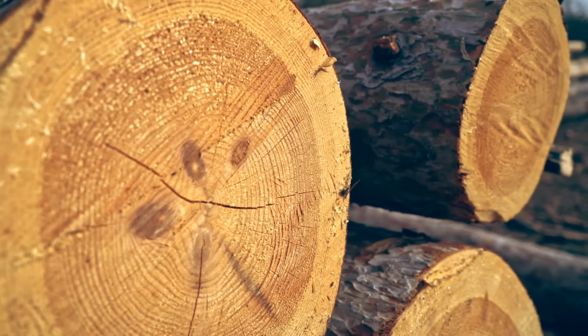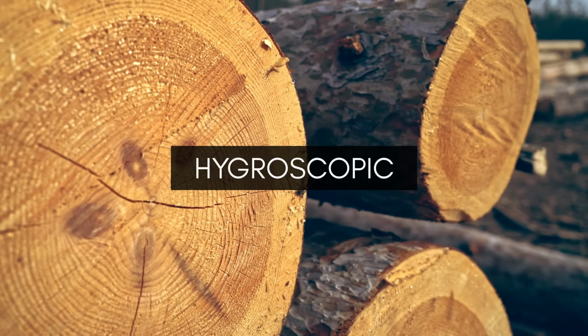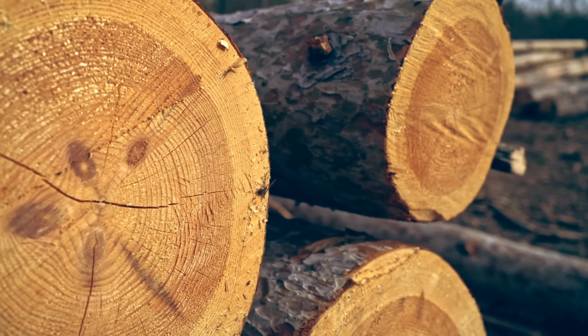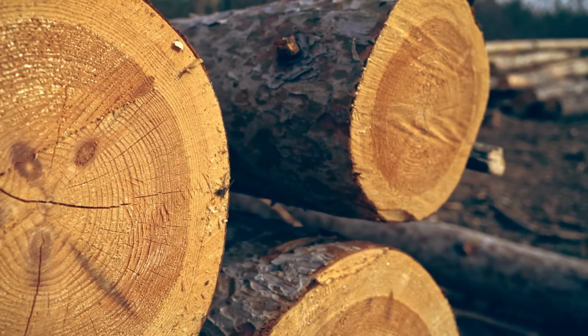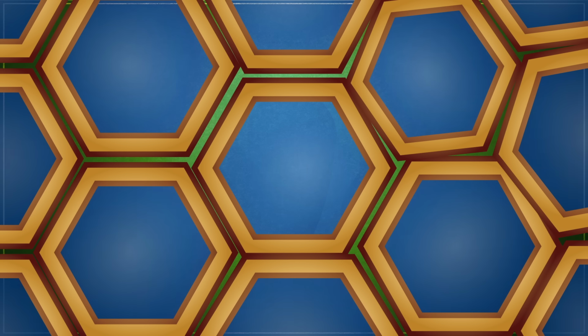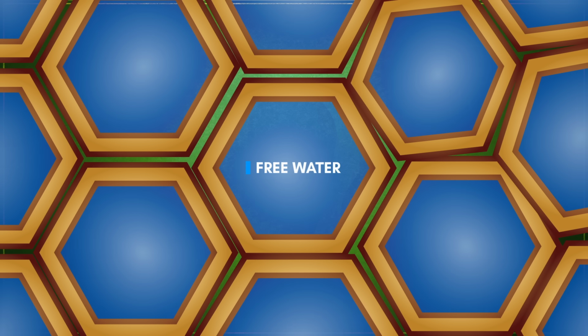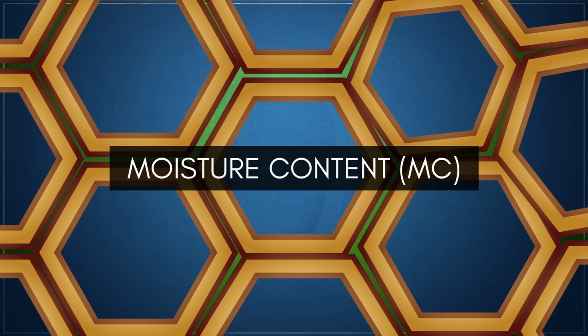Wood is inherently a hygroscopic material as it exchanges moisture with its environment in response to the ambient temperature and relative humidity of the air. Water exists within the cellular matrix of wood in two distinct forms: free water, which occupies the hollow cell cavities, and bound water, which is molecularly bonded within the physical structure of the cell walls themselves. A wood's moisture content, or MC, is the relative weight of water within it when compared to its oven-dried weight. On a freshly felled green tree, this can range from approximately 30% to over 250%.